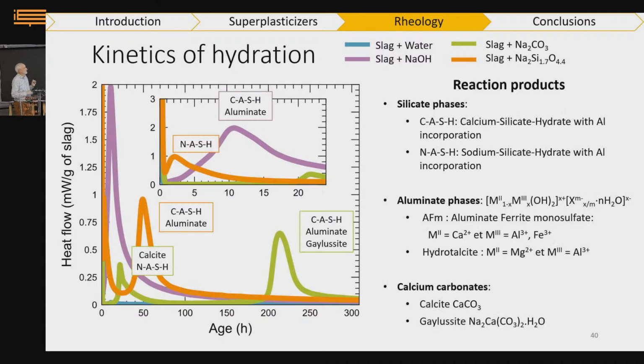So we go to my old love, NMR. This is a calorimetry, but with NMR we identify the different chemical events associated with the heat release. What's interesting is to look at what's going on at relatively early age, between the first 24 hours. You see that the system activated with sodium silicate is very different from the others at very short times. There's already a lot of heat release, and a lot of chemistry going on that can be associated by NMR to the formation of what we call an N-A-S-H gel, basically a hydrated sodium aluminosilicate gel, okay? And this occurs much earlier than in systems activated with sodium carbonate or sodium hydroxide.